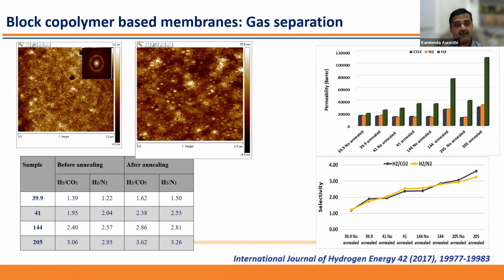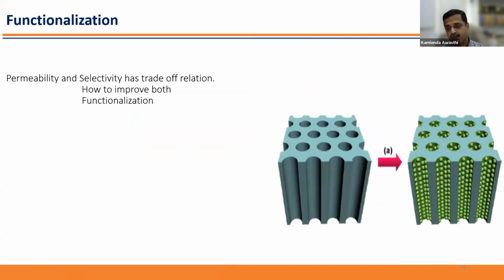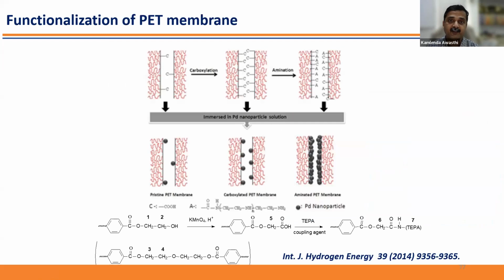Okay, so once we prepare the channel and we do the etching, we prepare this nano template. So how can we further improve? This is another possibility that we found, a very good way to functionalize them and deposit the nanomaterials that are gas sensitive. So here you can see this is the channel that is already created. Suppose I'm talking about this micrometer size membrane, so this channel has a micrometer size and you functionalize them, then you can put your gas sensitive nanoparticle inside this channel. So what will happen, the active diameter of the channel reduces, at the same time more gas can be diffused within this nanomaterial. So this may help to get better selectivity.